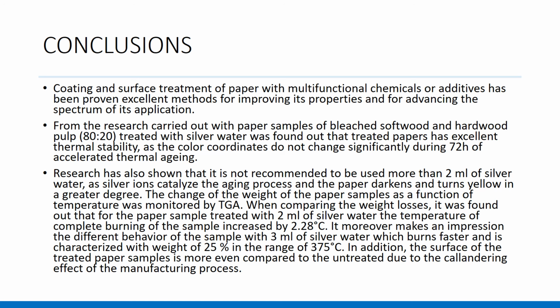Research has also shown that it is not recommended to use more than 2 milliliters of silver water, as silver ions catalyze the aging process and the paper darkens and turns yellow to a greater degree.